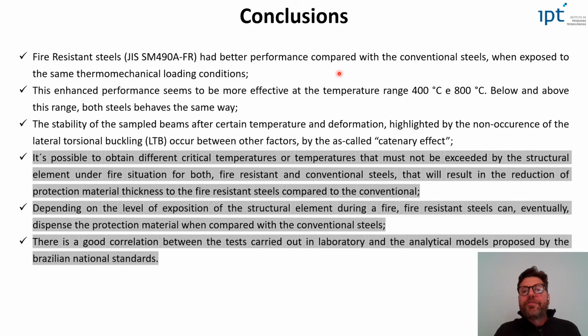Fire-resistant steels had better performance compared with the conventional steels when exposed to the same thermomechanical loading conditions. This enhanced performance seems to be more effective in the temperature range of 400 degrees to 800 degrees. Below and above this range, both steels behave the same way. The stability of the sample beams after certain temperatures and deformation, highlighted by the non-occurrence of lateral torsional buckling, occurs, among other factors, because of the so-called catenary effect.